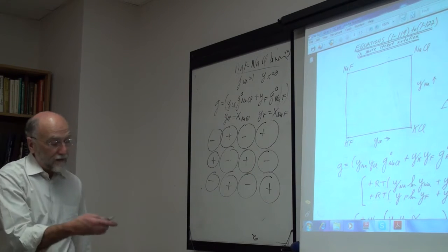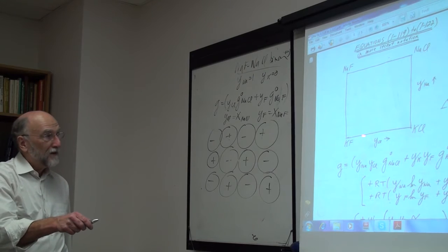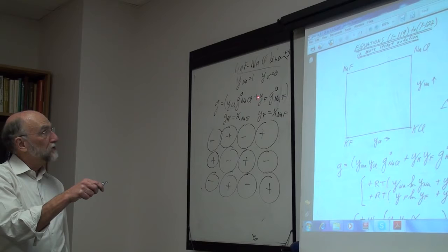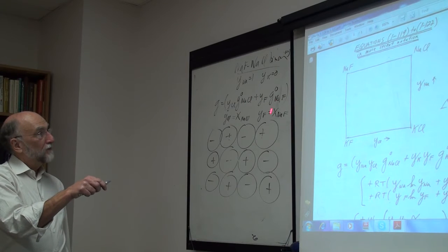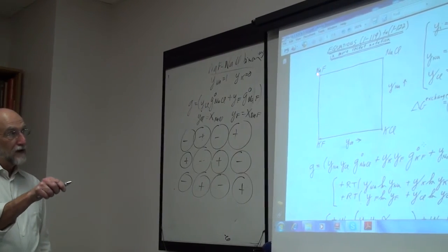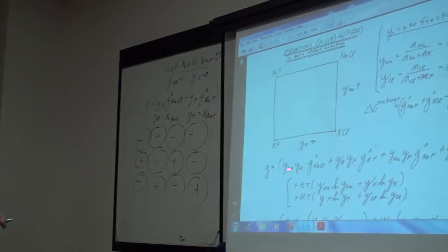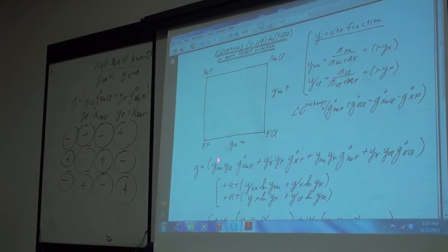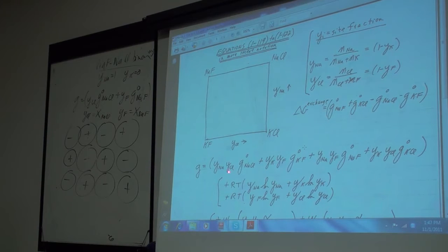How should we weight it if you went across here? In the KF-KCl system, you would get the same thing, Y chlorine times G naught KCl plus Y fluorine times G naught KF. How are you going to vary in between them? Let's multiply by the fraction of the sodium-potassium ratio. So this is G naught sodium chloride times the fraction of sodium times the fraction of chlorine.